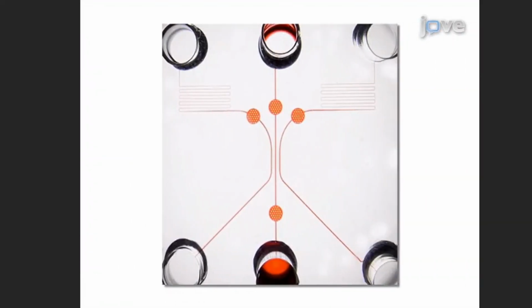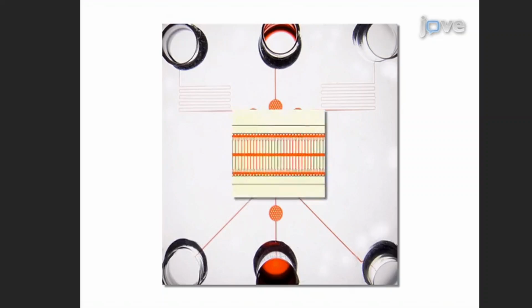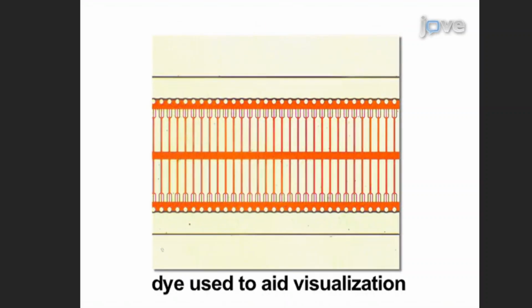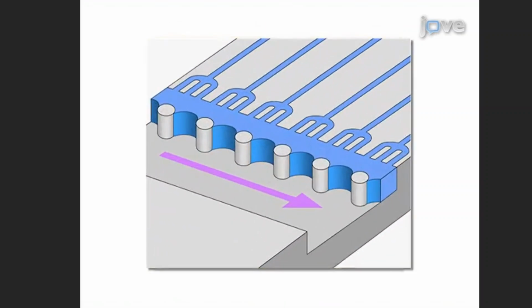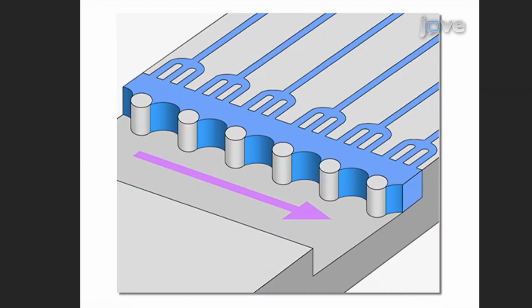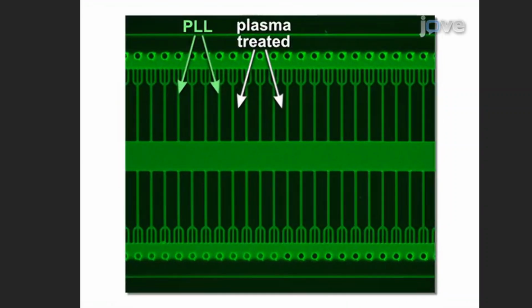The second step is to pattern polylysine within the microfluidic device. This is achieved by filling the device with polylysine, allowing a water mask to form by evaporation, and then using a plasma treatment to remove the exposed polylysine to create the biomaterial pattern.